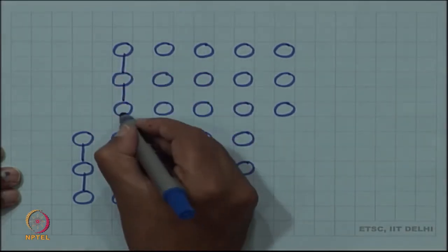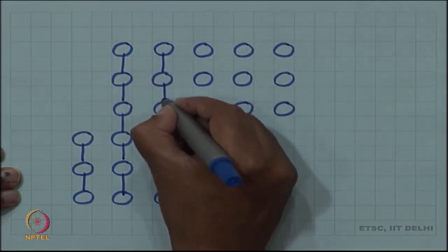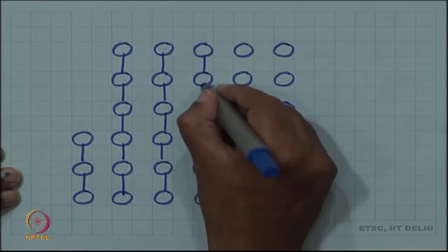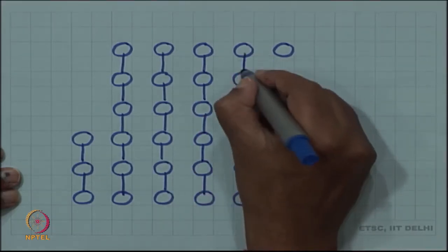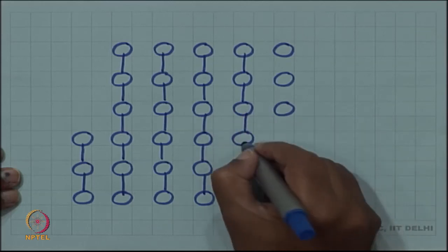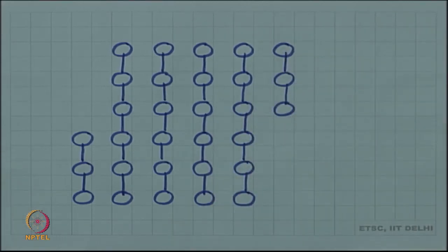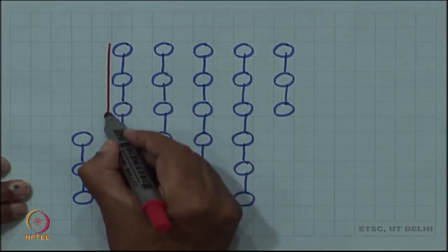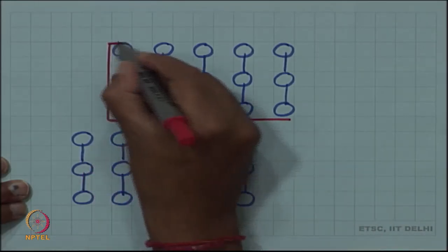So, you can see that in the final deformation, in the end we have achieved the same configuration which we would have obtained by a complete single step rigid body deformation of the upper half of the crystal with respect to the lower half.